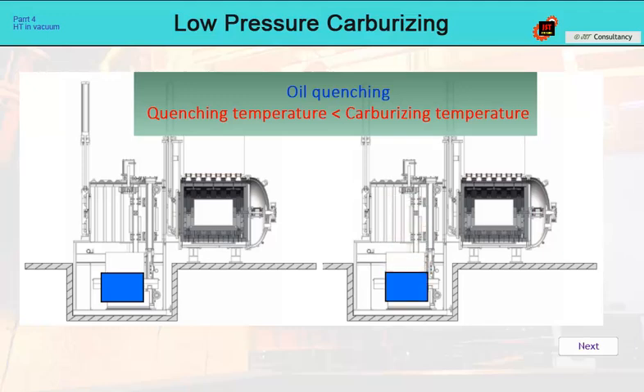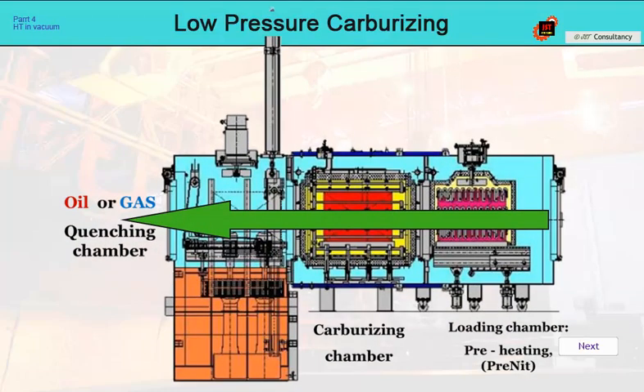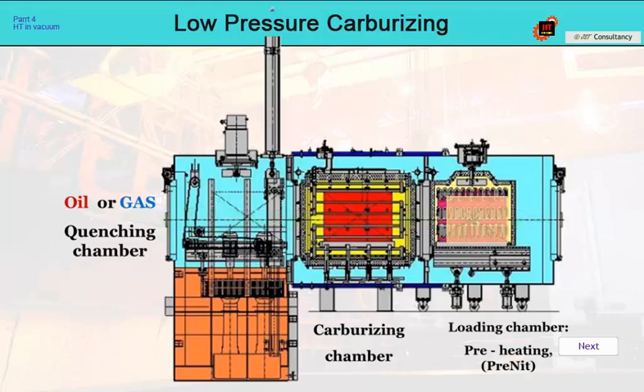This is a similar procedure to that of multipurpose furnaces with one-sided loading. The condition is that the furnace's handling mechanism must work in both directions, that is, there and back. If it is only one way, we must always make pre-cooling in the heating chamber, or we must slowly cool the batch in the quenching chamber, take it out of the furnace and return it back in front of the first chamber. Then heat it again, this time to the optimal quenching temperature, and then quench. The energy consumption will be almost double, and the process time will be 50% longer.